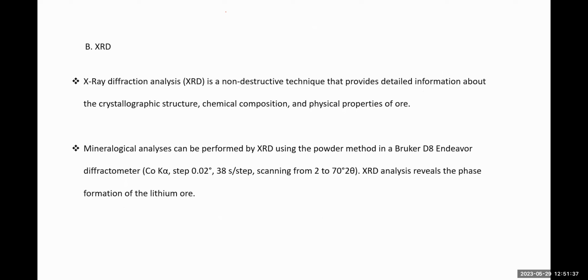And XRD also gives you phase differentiation. XRF and AAS cannot tell you the type of spodumene, the type of lithium. XRF, ICP-OES and the likes of them will not tell you the type. But with XRD, with phase differentiation, it's going to tell you which lithium ore is present on the site. Please look at the next slide.